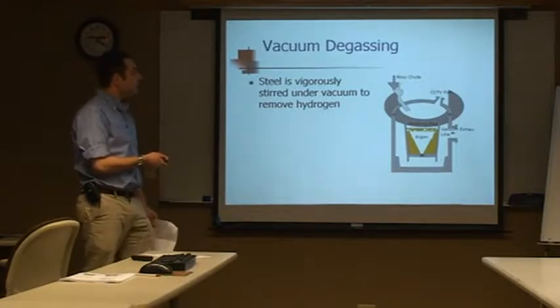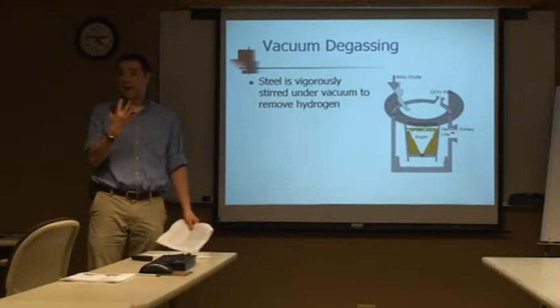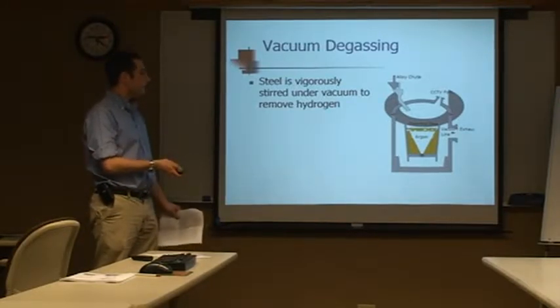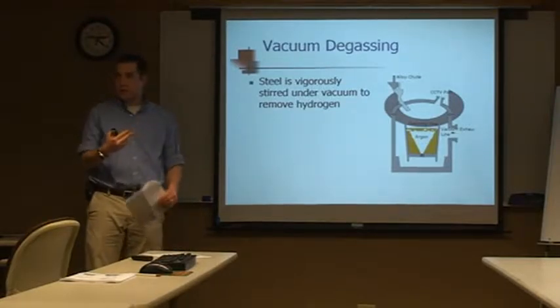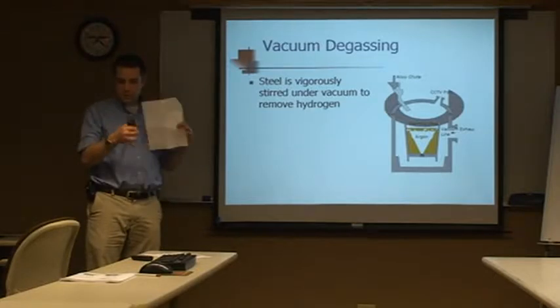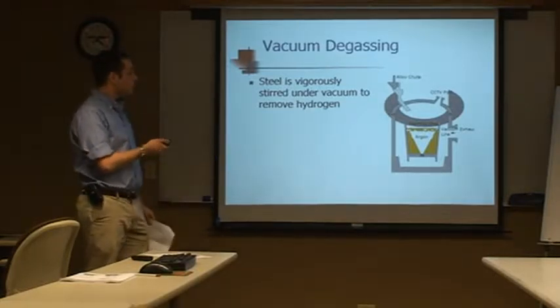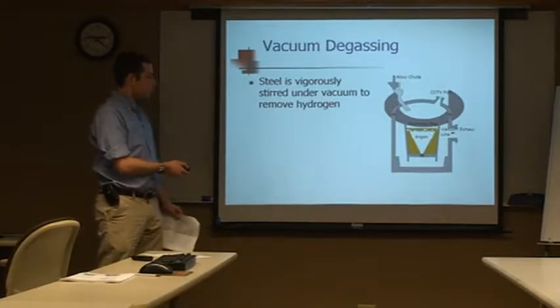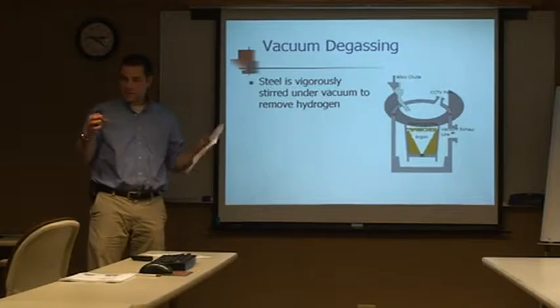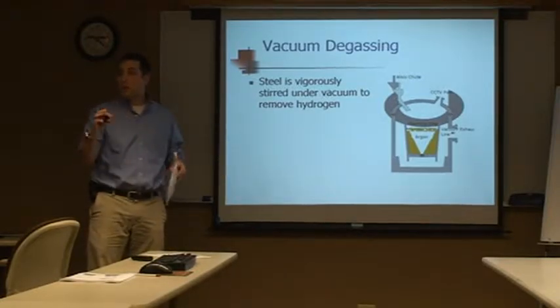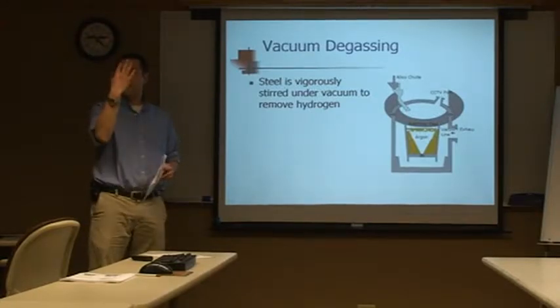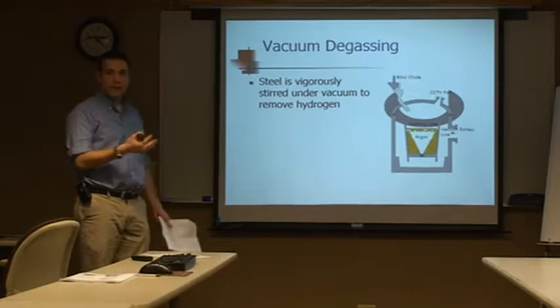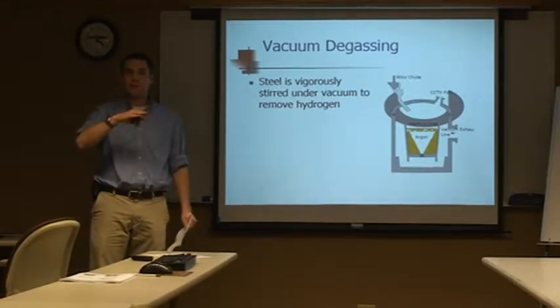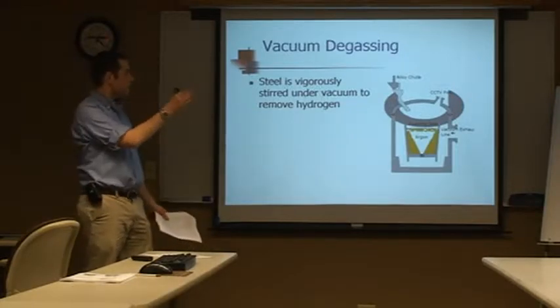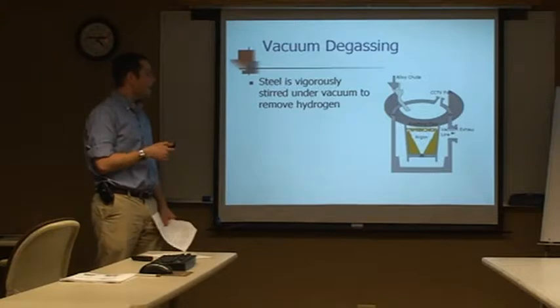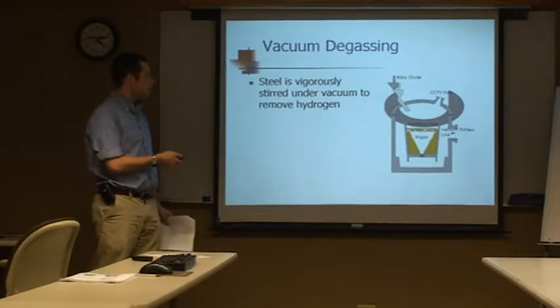But in order for this to be effective, we need to expose as much steel as we can to the vacuum. So we'll use a dual process, which was mentioned in the video, the induction stirring process, which again turns the steel over and it'll expose that little window of steel to the vacuum. But we also do argon bubbling, which is we jet in argon from the bottom of the ladle, and as a gas, it bubbles up through the liquid, hopefully capturing some hydrogen as it goes up and into the vacuum and out, and that cleans out some hydrogen that way. It also disrupts the surface of the liquid steel, which again exposes more steel to the atmosphere and or to the vacuum, and lowers the hydrogen content of the steel.